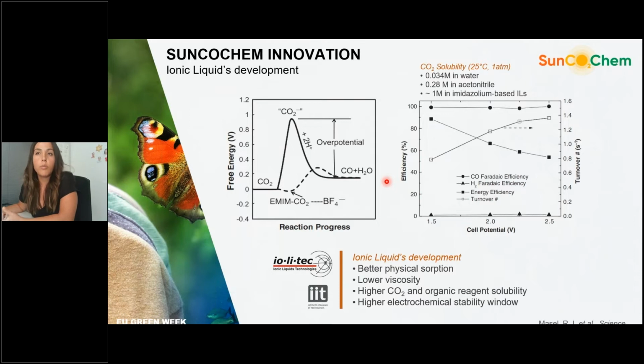Something also very important to obtain a device with very good efficiency is how robustly your device delivers the CO2 to the electrode surface. That's why, instead of aqueous electrolytes, we are using imidazolium-based ionic liquid electrolytes. As you can see, using these electrolytes, we can increase the CO2 solubility up to 30 times in comparison with water electrolytes. Those ionic liquids have very good properties for this kind of technology: better physical absorption, lower viscosity, higher CO2 and organic reagent solubility, and higher electrochemical stability. The imidazolium can also interact with the CO2 radical anion species that is necessary for producing CO, lowering the potential of the reaction and the overpotential of the whole process. So in the end, they also act as a kind of co-catalyst of the system.